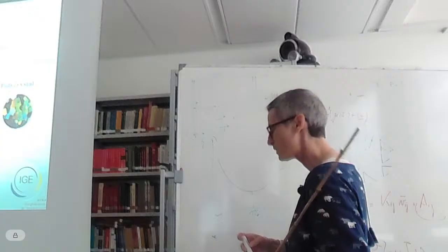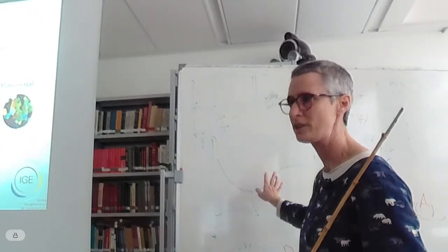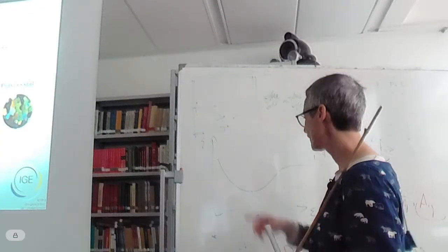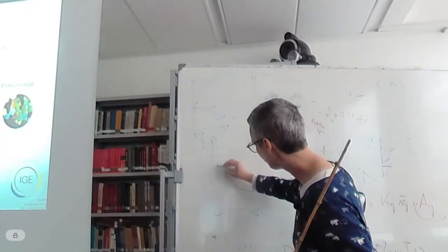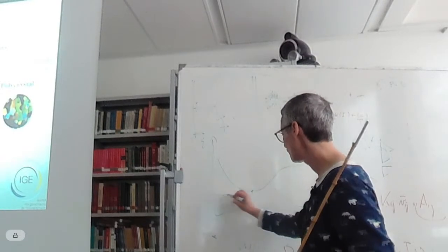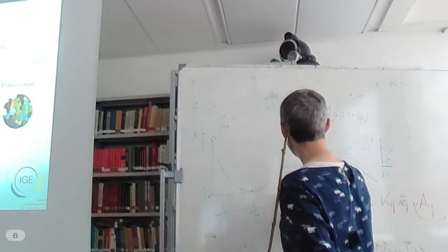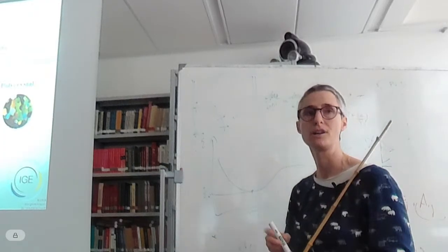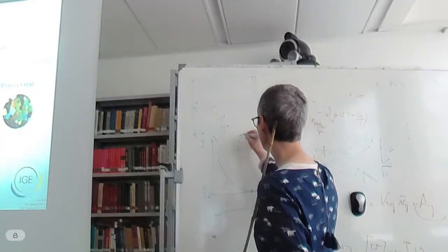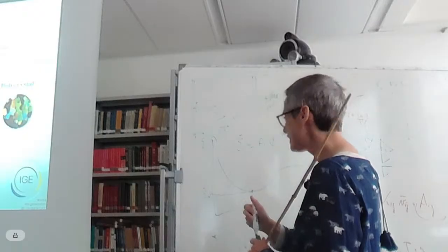And it has been tested for many, or at least what we can do in the lab, temperature conditions, stress conditions, and so on. And so Glen got this curve here. And he noticed that you can relate this epsilon dot mean to the stress at which you've done your experiment, and so you get a law that is epsilon dot proportional to sigma to the power n. And this is what we call the flow law.